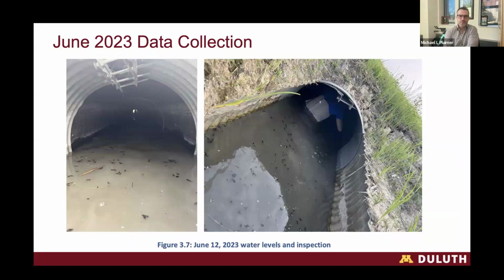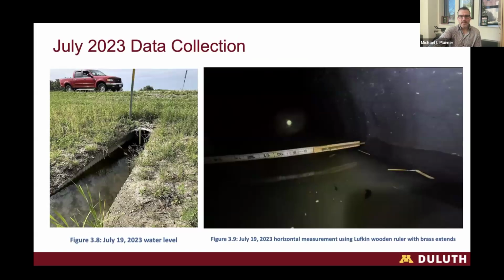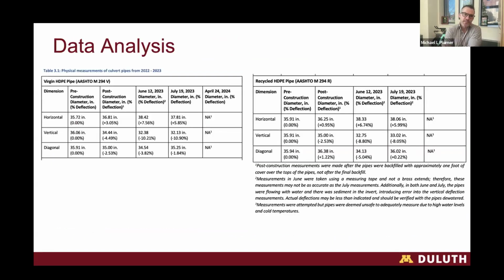I give her a lot of credit for going in there, but this was the end of our inspections on these just because there was not a good way without dewatering the pipes, which is really what we're going to do next on this, is to do a complete dewatering and full inspection of them. That said, she was able to gather some data, both horizontal and vertical deflection measurements, but due to the sediment in the pipes and how much material was flowing through these pipes, it was very difficult to get accurate vertical and horizontal deflection measurements. So the measurements here should be taken with a little bit of a grain of salt, or a grain of sand or backfill material, if you will.